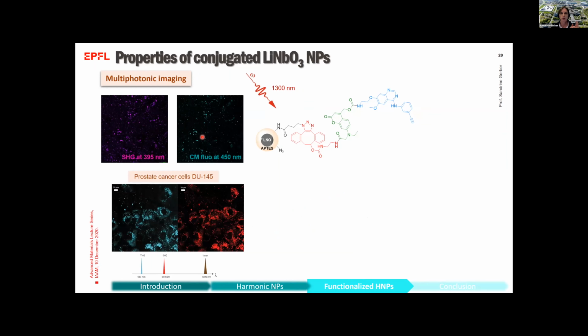Then we also imaged those nanoparticles at a higher wavelength in order not to trigger first the release of the molecular cargo, but just to see if we can make the imaging, for example, of prostate cancer cells, as you can see here on those pictures, by retrieving the third harmonic signal and the second harmonic signal, which are colocalized.